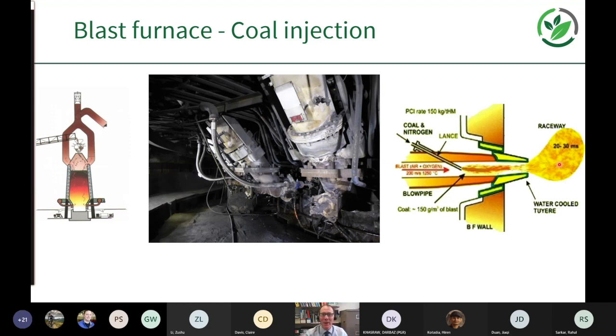And the raceway is where sometimes you've got enriched oxygen which is injected into the furnace, and this is where the temperature really ramps up and you get combustion, or partial combustion, taking place. So you get heat generation, and you get the production of carbon monoxide, which is the main reducing gas in the process. You also get production of a certain percentage of hydrogen, depending on the type of coal that you're using as well.